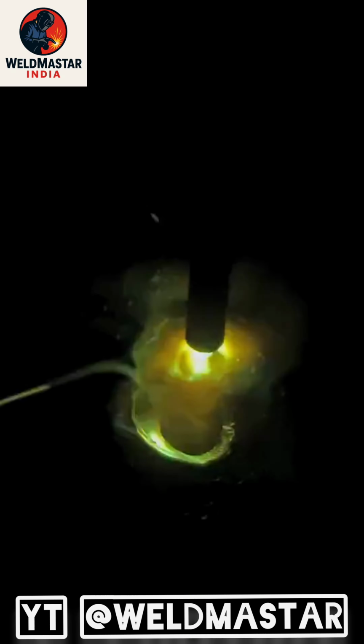During the process, do not pull the weld inward too fast. If you move inward too quickly, the central temperature will increase. Once the molten pool temperature rises, the hole will not close properly and may actually become larger. So while welding, use this heat-controlled, gradual hole-filling method, continuously moving inward step by step.